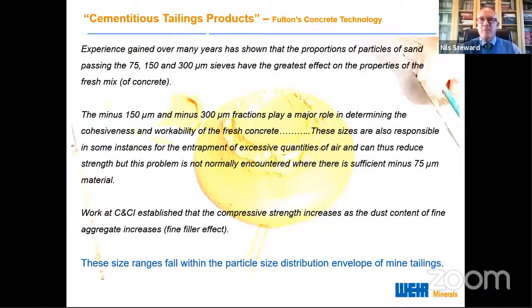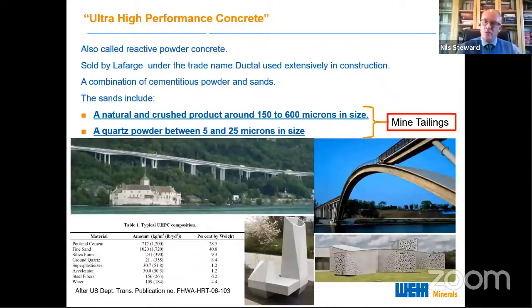If we now extrapolate this to the real world, ultra high performance concretes, also called reactive powder concretes, is becoming a very well established product. It's actually been sold for many years under the trade name Ductal by Lafarge, and it's a combination of cementitious materials and sands. Those sands typically being 150 to 600 microns in size, and a filler between 5 and 25 microns in size, of course. And this is well within our mine tailings regime.